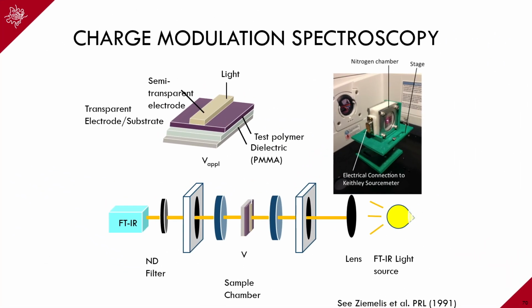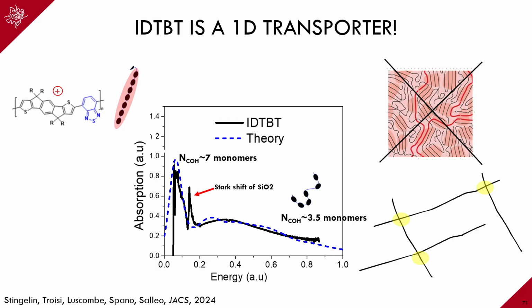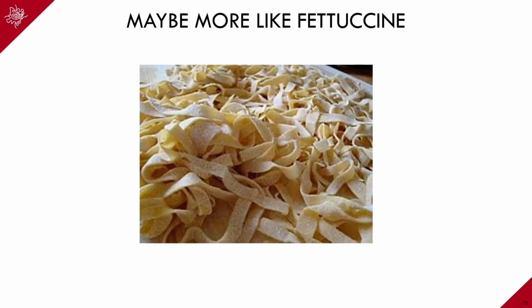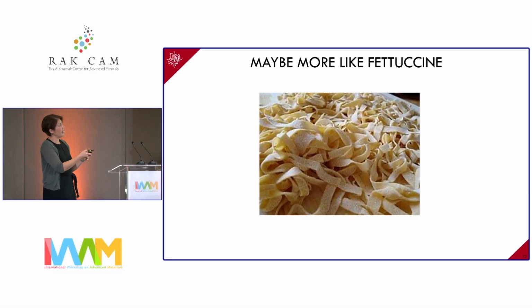So here again, we use charge modulation spectroscopy. And here, it really confirmed this idea that was developing, which is that these rigid rod polymers are very much 1D transporters, unlike the classical polymer P3HT that we have. And these days, the model we have, well, ultimately, it is a polymer. It's not a plank. So the idea that we have is, OK, we're moving away from spaghetti, and we have more of a fettuccine-like structure. So you have these wide ribbons, and these wide ribbons are weaving through.